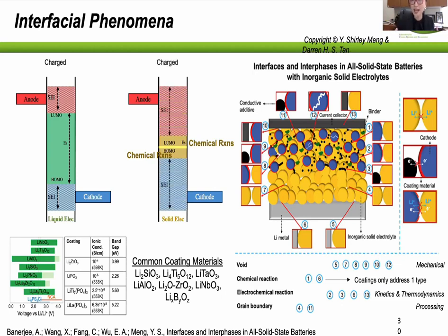So the SEI comes into play. And we wrote in this Chemical Reviews paper, there are so many interfaces, you don't even know where to start. Because in a solid, the liquid cannot flow, right? Sorry, the electrolyte cannot flow. So if you have a defect or a crack, that's a new interface, because the electrolyte cannot flow.